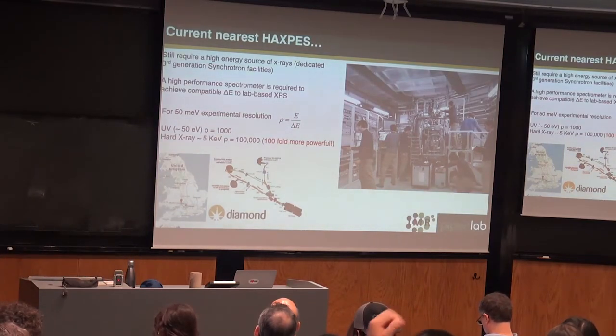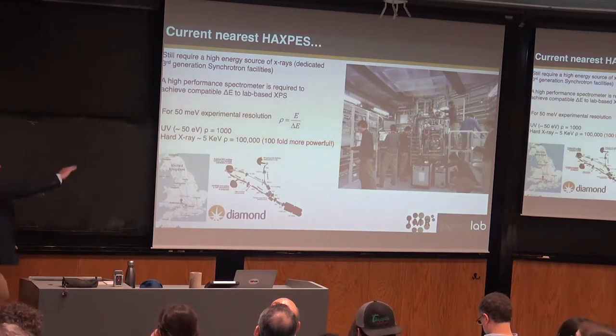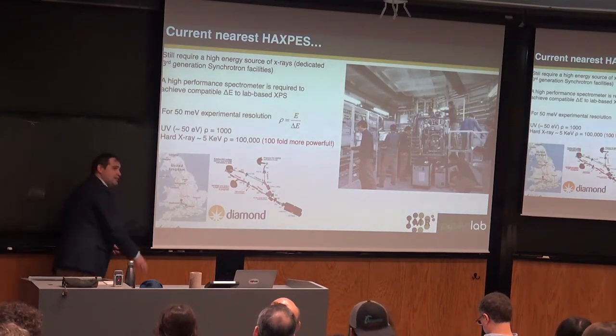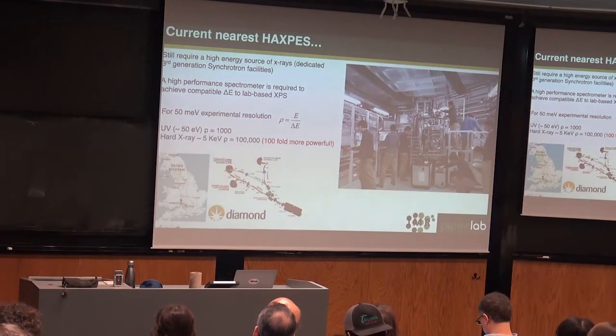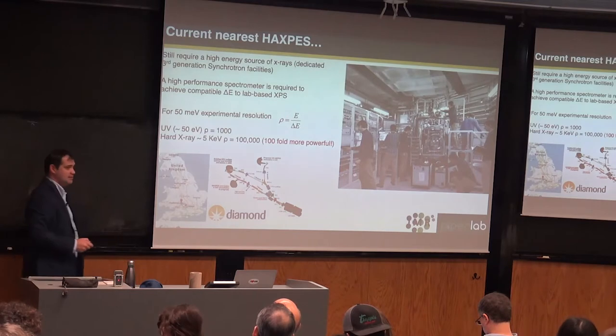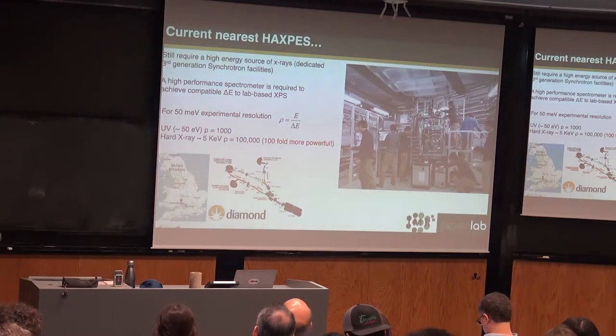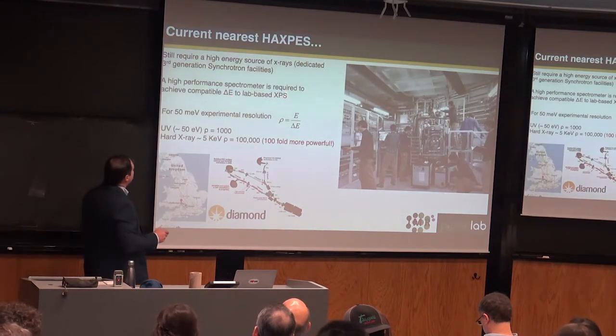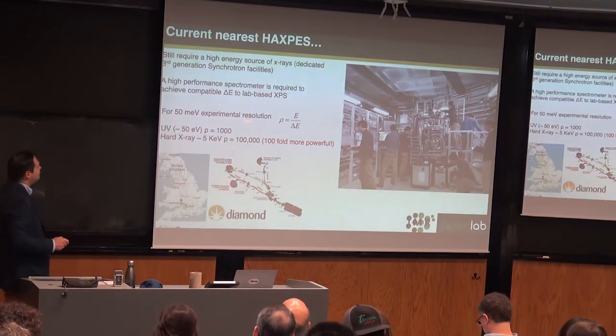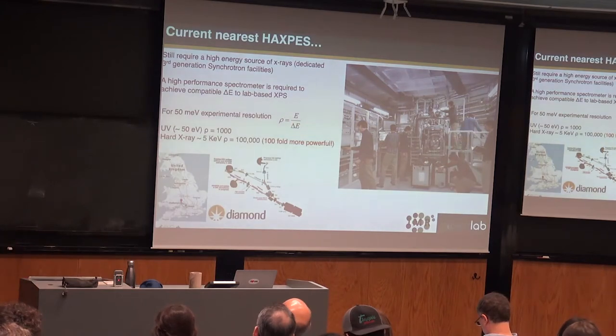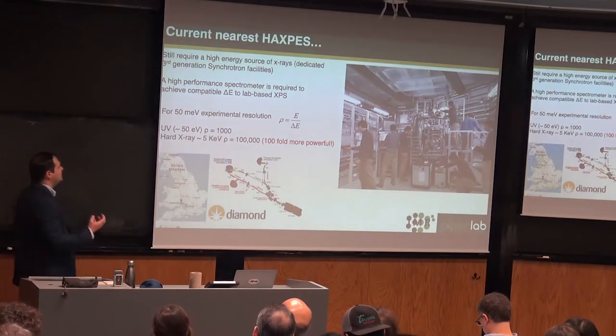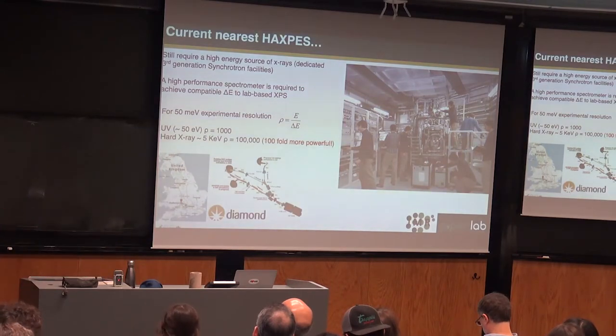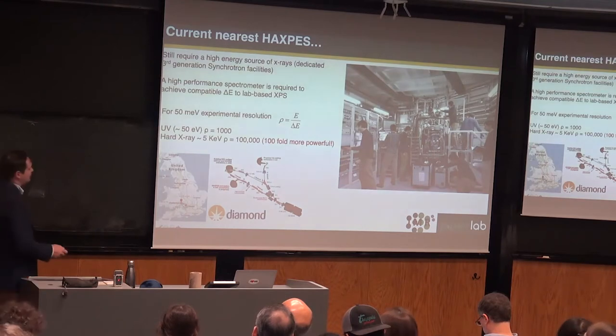But it took a long time before HAXPES became a real thing. The reason for that is because you are going to energies way above your absorption edges, and so your cross-section plummets as a power law of -5/2. So it plummets really quickly, and so you need brighter sources, and the first thing is you would need a synchrotron. The second thing is that your resolving power depends on the energy you're at, and when you're interested in the valence band region, the binding energy will be near zero, and your kinetic energy will be mainly whatever light you put in.